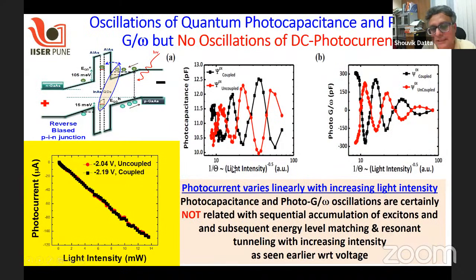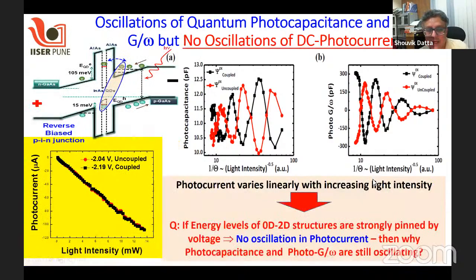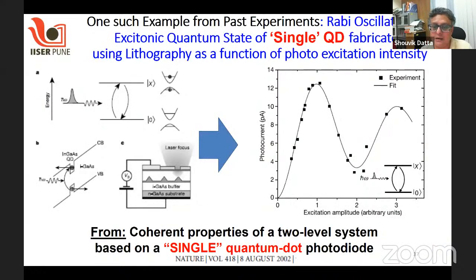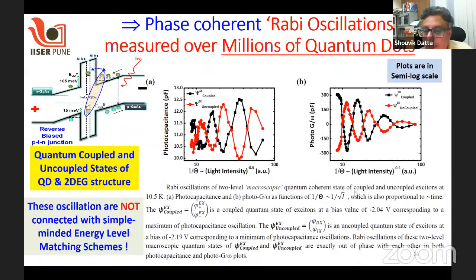And once you sit there at one particular voltage and just vary the light intensity, you begin to see these very nice oscillations. We think that if the energy levels are strongly pinned and there are no oscillations in the photocurrent, it clearly shows that there is no sequential energy matching leading to such oscillation. And looking back at whatever results people did earlier with single QD, we can now say that these oscillations are possibly the phase coherent Rabi oscillation measured over millions of quantum dots.